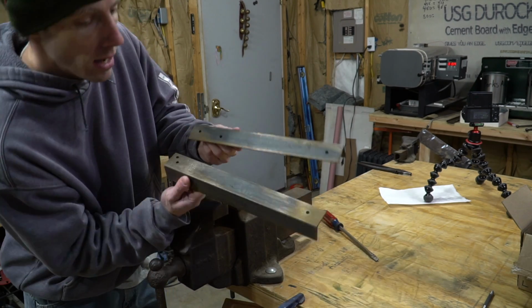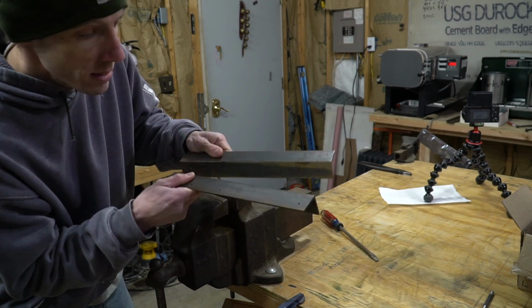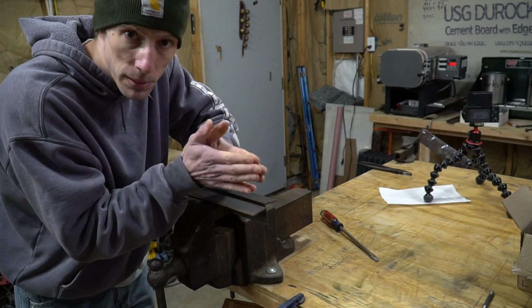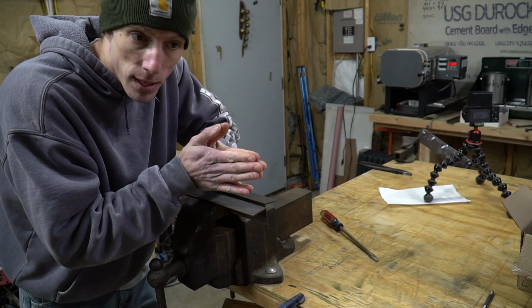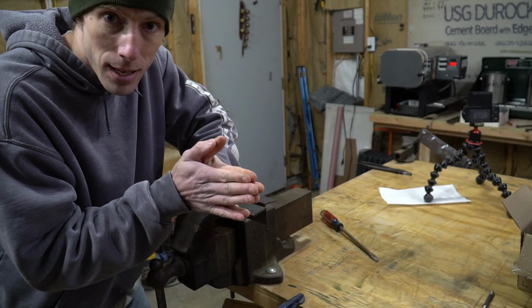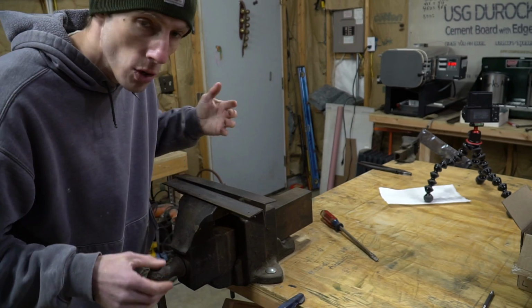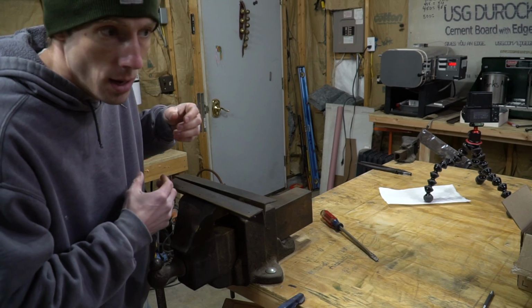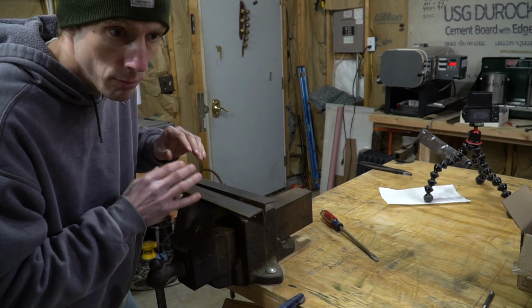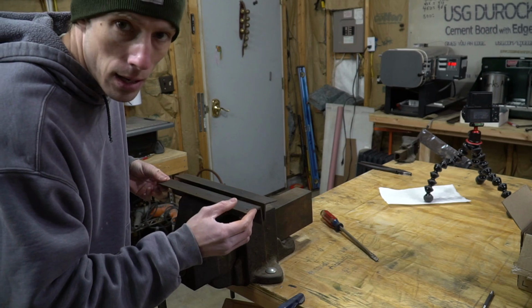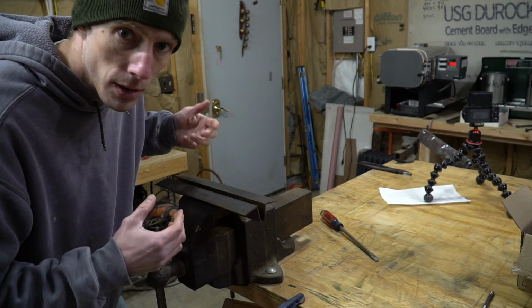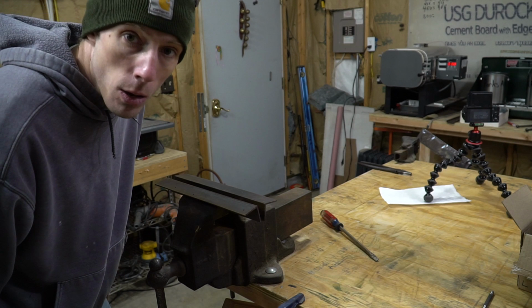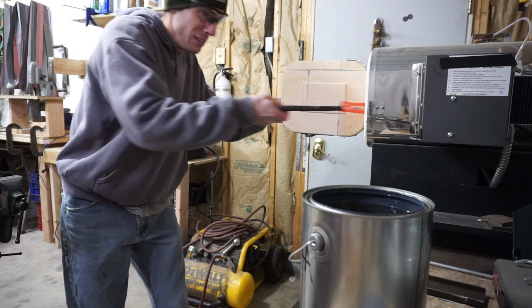These have been somewhat flattened and straightened, so they're perfectly straight. And this is going to force our blade to continue cooling and to continue to form that martensite in a completely straight position. So hopefully this will take care of most of our warps. So far this has done a really good job for me in mitigating warps. We still might have a very slight one depending on a couple of things, but we'll see. Okay, so our austenizing cycle looks like this. Ramp as quickly as possible to 1475 degrees. No soak time as soon as it hits 1475. Quench it in Parks AAA.